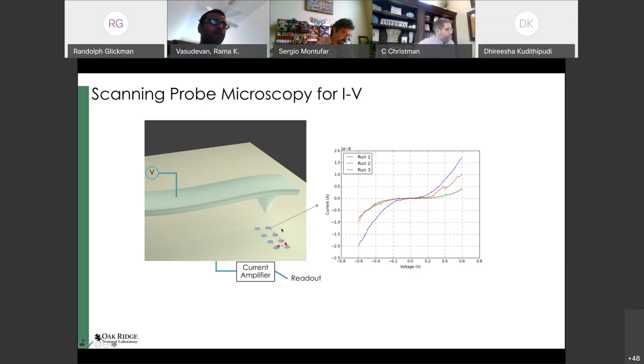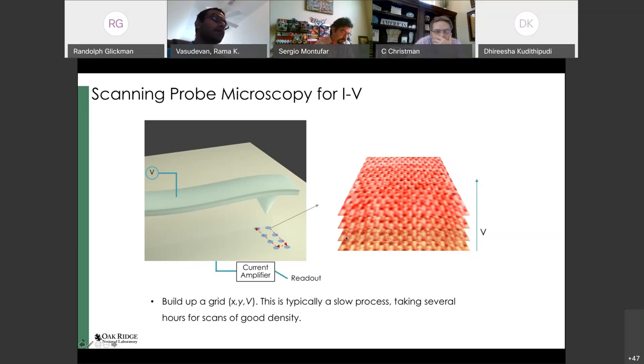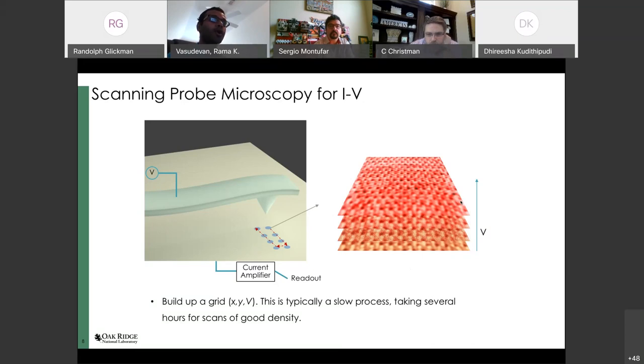Repeating this spectroscopy over a grid of points builds up a hyperspectral data set — voltage slices of current at different voltage levels. This is the state of the art for nanoscale electrical property mapping. One particular problem, however, is that it's typically a slow process — it takes several hours to create a scan of good density. If we're spending several hours for a scan that might only be 20 nanometers across, the system has to be extremely stable; otherwise dramatic drift will prevent correlating atomic positions with electrical properties.